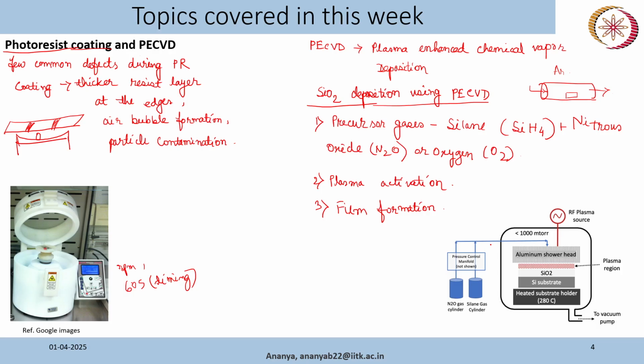I don't think there is a single best technique for deposition, because it depends on what purpose you are using it for. Ideally we want a faster deposition rate. But if you do it very fast, say in sputtering, where we apply a lot of RF power and provide argon gas so that the rate is high, that will not lead to a very good quality film. There will be a lot of defects. So a controllable slow rate will always give a better quality film.